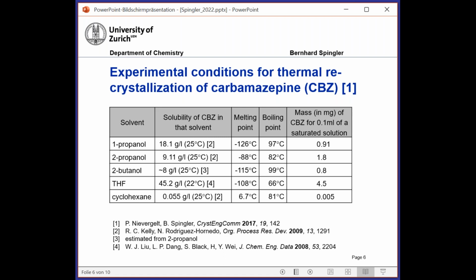However, the solubility was so low that we could do the experiment, but in the end, the growing crystals were not big enough for our machine at that time. So essentially, by choosing the solvent, you can choose how much material you will use. And one important point, and this is different to the isothermal crystallization, is that you need to start at room temperature with the suspension. Because most simplistically, you would start at room temperature, you would heat up your system so that saturation is happening. And then when you slowly cool down, crystallization occurs. Again, at room temperature. Of course, you could also do the experiment in such a way that you would go below room temperature, and this is possible with the machine.